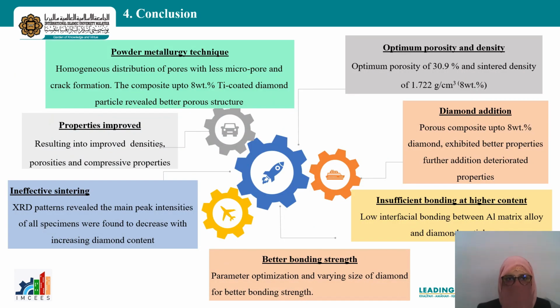Thus, we concluded that the powder metallurgy technique allows formation of a homogeneous distribution of pores, micropores, and prevents the formation of cracks. And also, the optimum porosity and density were obtained at 8%, that is about 30.9% porosity, and the density is 1.722. And the properties improved as a result of this good porous structure. Because of the addition of the diamond, the properties only improved up to 8%. Beyond that, it deteriorated. And there is insufficient bonding at high content, and also at the aluminium and diamond interface.